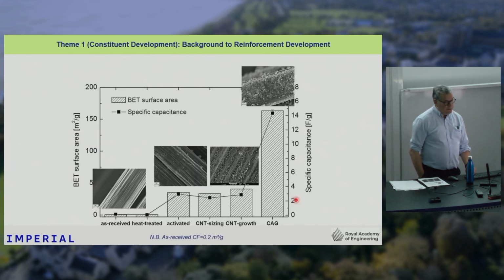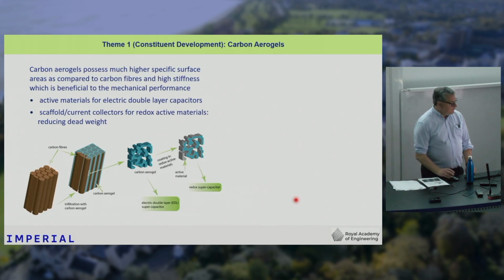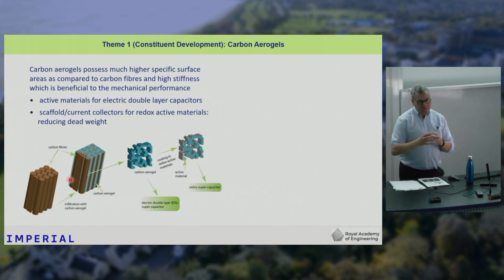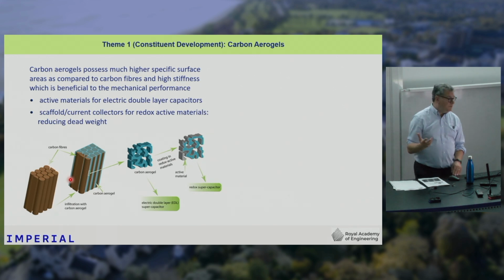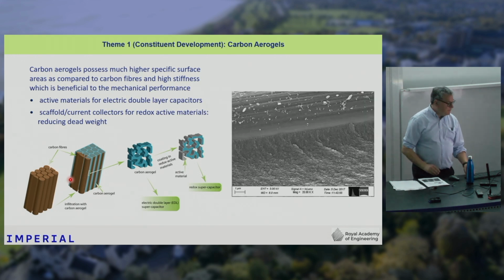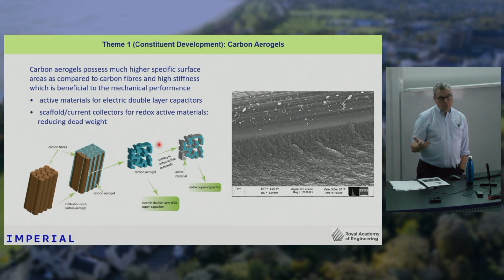But what we've really moved on to is carbon aerogels. Just to explain what carbon aerogels are, these are effectively amorphous nanocarbon foams. It's produced by infusing a precursor into the carbon fiber fabric, and we're just using conventional aerospace grade carbon fibers, and then you pyrolyze that to turn it from a resin, effectively a phenolic resin, into a carbon aerogel. This is an image showing a carbon fiber which is about 7 microns thick, and then this is the carbon aerogel within the matrix space between those layers. Carbon aerogels are used widely in the conventional electrochemistry field for supercapacitors and even batteries.